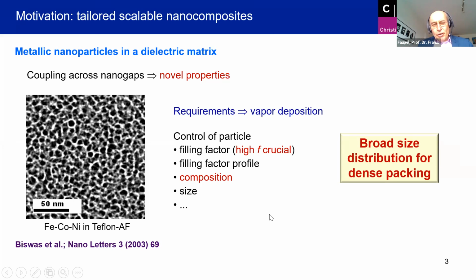And different from most approaches, we are not so much interested in monodispersed particles. We, by intention, strive for a broad particle size distribution. This allows us to have a very dense packing of these disordered nanoparticles, and then we can take optimum advantage of processes occurring on the nanoscale, so particularly quantum mechanical processes, plasmonic effects, etc.